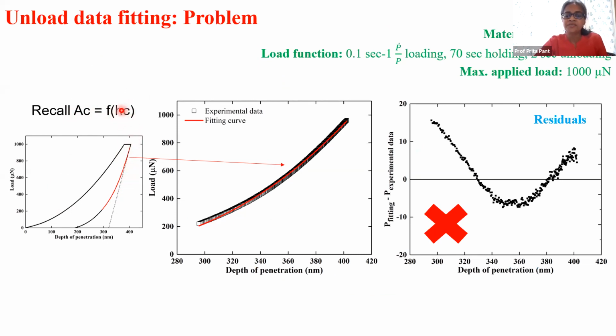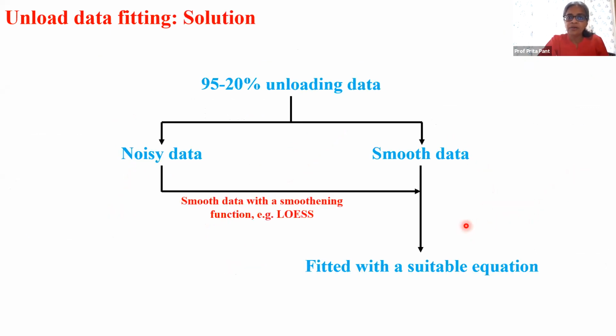So if I'm making mistakes here, it'll reflect in my other calculations. So this is the unloading curve. This is now data from SU8. And you look at this fit, and if I just look at it, it looks kind of okay. But now you plot the residuals and they look really bad. So again, you need to look at the residuals and then take a call as to what you need to